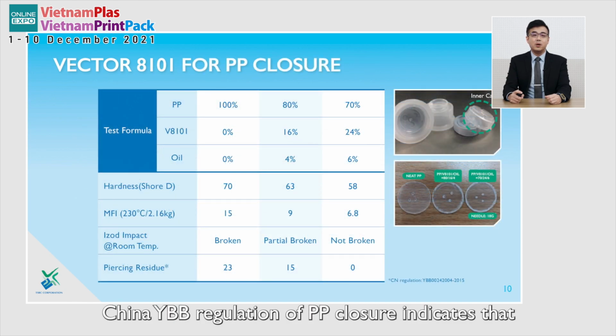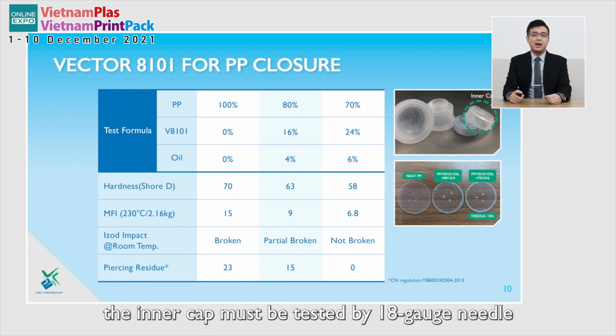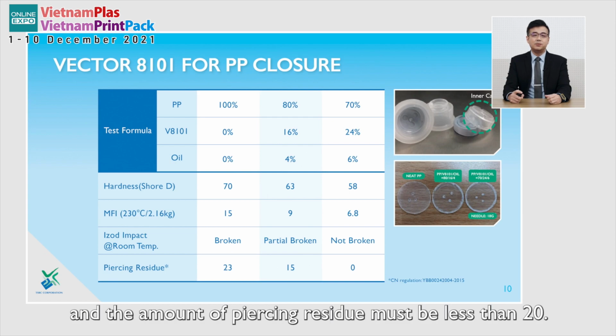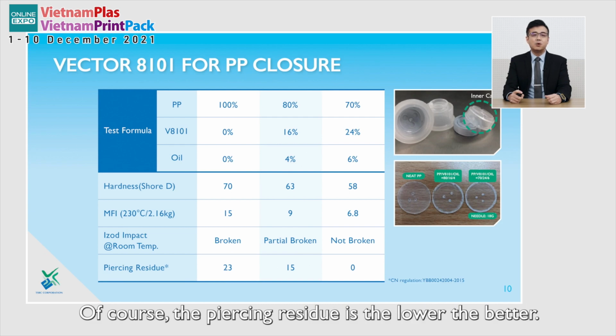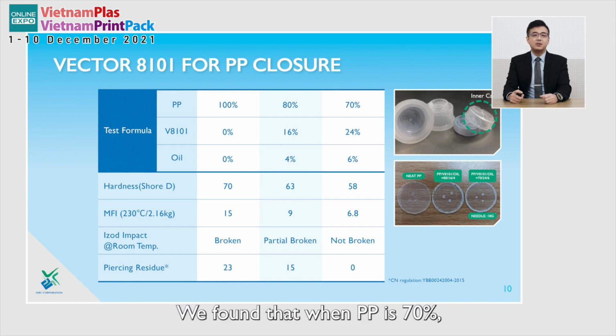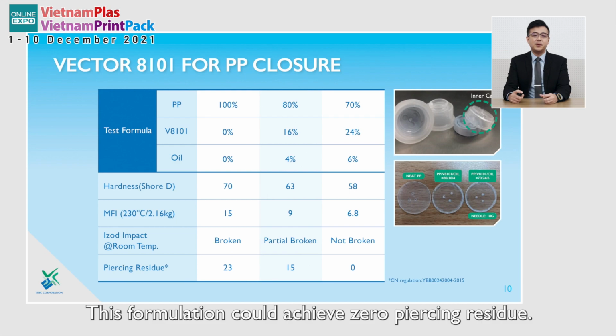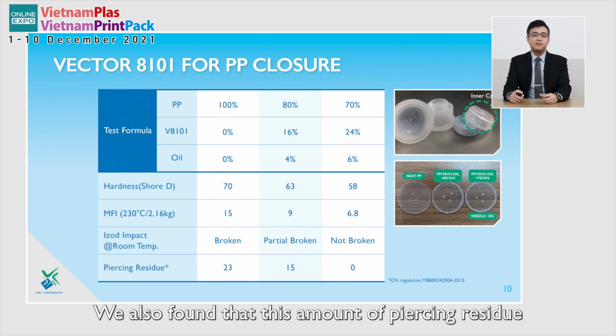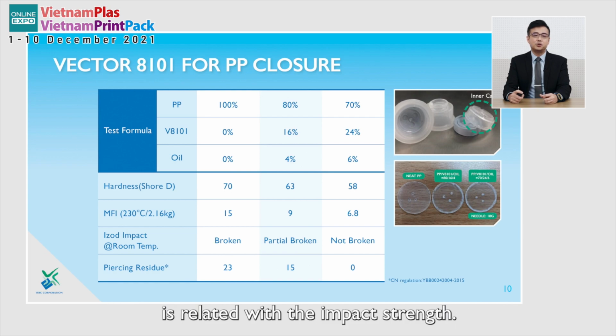China YBB regulation of PP closure indicates that the inner cap must be tested by 18 gauge needle, and the amount of piercing residue must be less than 20. Of course, the lower the piercing residue, the better. We found that when PP is 70%, 8101 is 24%, and the extended oil is 6%, this formulation could achieve zero piercing residue.